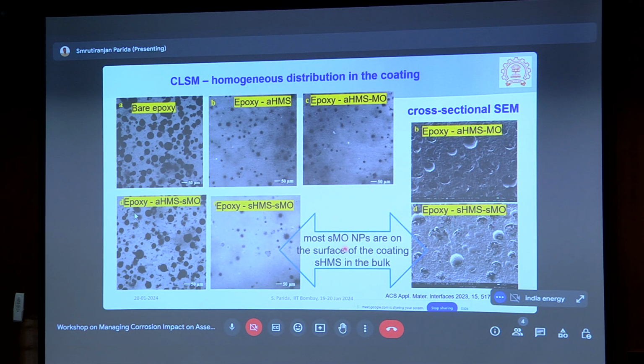What this slide basically says is that if we add these two components, the sMO and aHMS, to the material, how they get distributed on the coating. This is a confocal laser scanning microscope, and you can actually trace the hollow microspheres on the surface of the coating, and also in the cross section. This is the cross section. So we can see that in the bare epoxy, the hollow microspheres are distributed in this way.